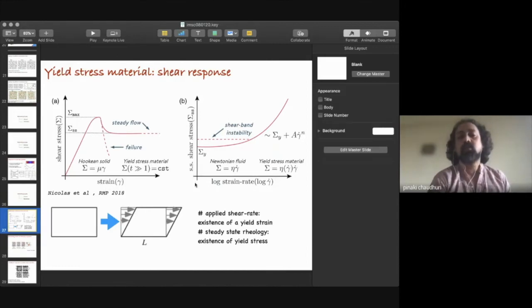And you can apply different rates of deformation, and you can plot the shear stress that is developing inside the system. What is characteristic of these glass forming systems is that you need a certain stress threshold for the system to flow. So imagine you have tomato ketchup or toothpaste. You need to apply a certain force for either the ketchup or the toothpaste to flow out. So that is the yield threshold for this system.